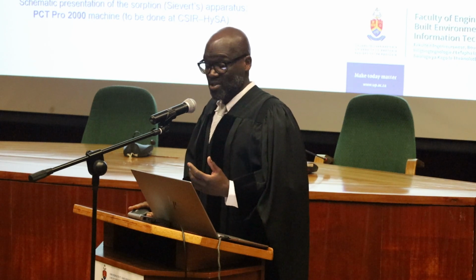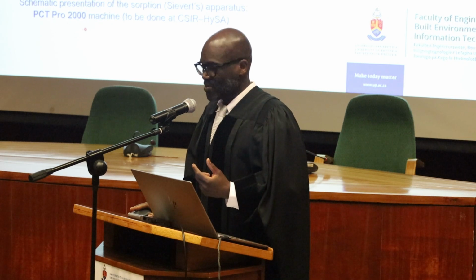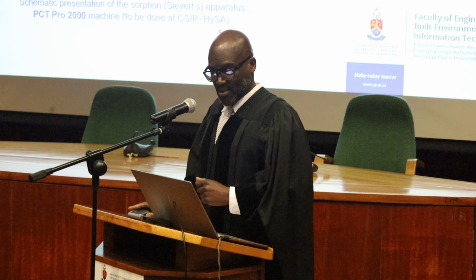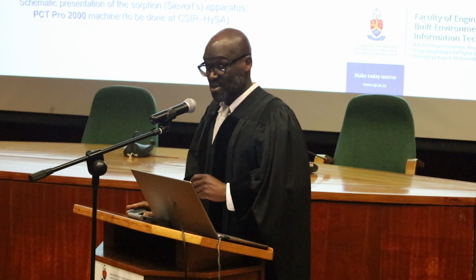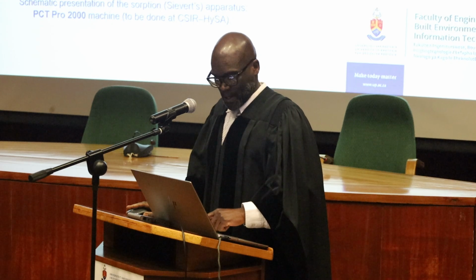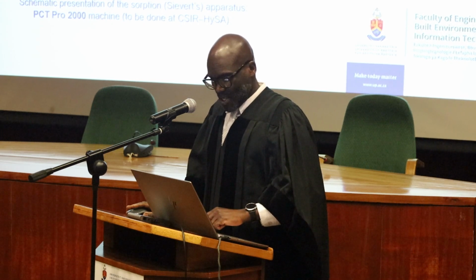The next phase now will be to test to validate the hydrogen storage capacity. That will be done using the PCT Pro 2000 machine or its equivalent. We are going to use one here at CSIR, at Hydrogen South Africa. And this is just the schematic presentation of the machine. If you know these two volumes and you know the pressure, if you open this valve, you should be able to measure the hydrogen absorption of this material. And out of that, we are going to generate curves like this. Now, this will be in practice, and it will be compared to the modeled materials.